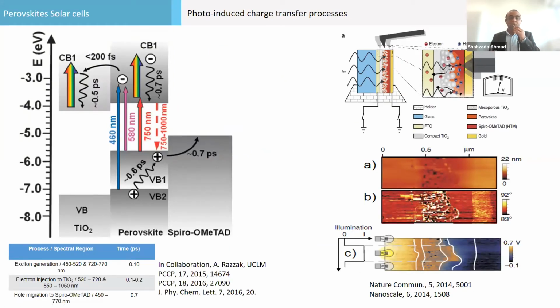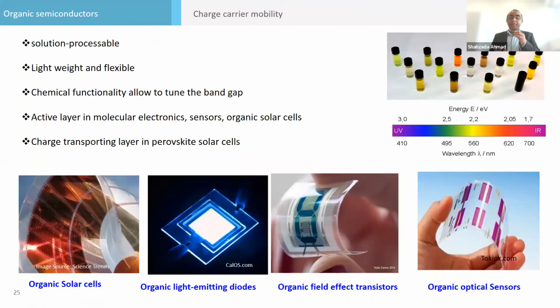We are interested not only in the electrical merits to know the device kinetics, but also in ultrafast spectroscopy and Kelvin force microscopy, to know the different mechanisms, different charge transfer rates, what is going on, because all this knowledge allows us to develop new materials. Like here, with the 120 femtosecond ultrafast spectroscopy and the Kelvin probe, we learned that there was a blockage at the hole transport layer because the spiro is not able to efficiently extract all the holes. So there was a traffic jam here at the interface between perovskite and HTM. So all this allows us to develop new materials, and we developed new materials, different types of organic semiconductors.